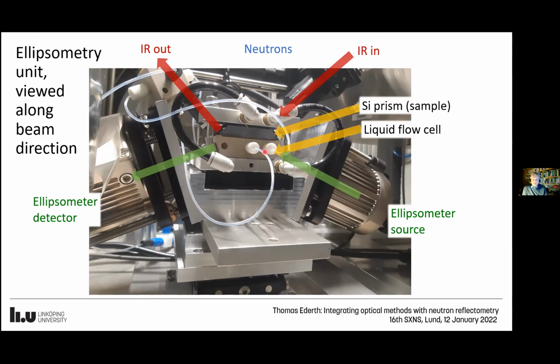Beneath is a liquid flow cell, and this liquid flow cell has optical ports for the ellipsometric system. So in and out at about 60 degrees angle of incidence. And from above, we have infrared light probing in a 3 reflection setup on this trapezoidal prism, and it's exiting on the top side also.